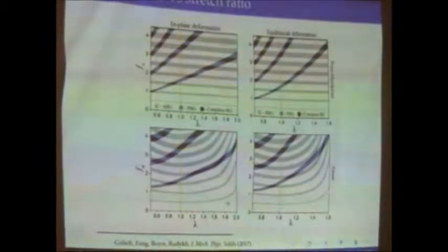In Gent material, you also see that shear band gaps change, and I'm going to explain it in a little more detail. What happened is that the pressure band gaps change mostly because of the change in the geometry. You just change the thickness of your layers as you pull, and pressure waves typically will not care about the changes in the material unless you really have very compressible, sort of auxetic, materials. Then you can also affect the pressure waves through the change in the material properties.